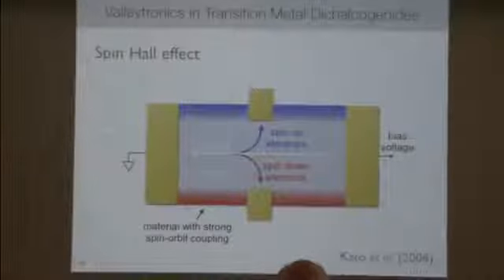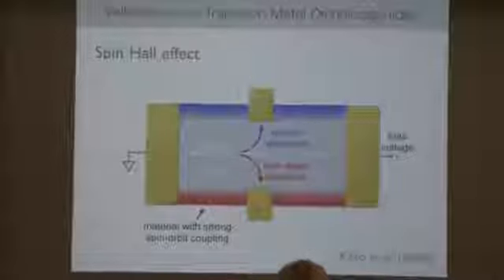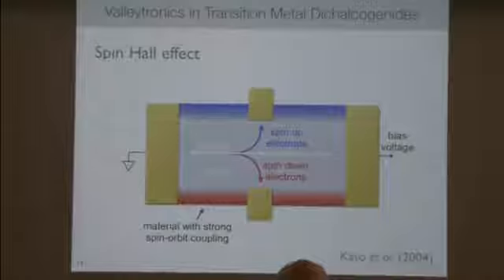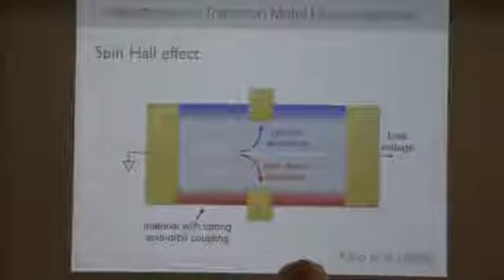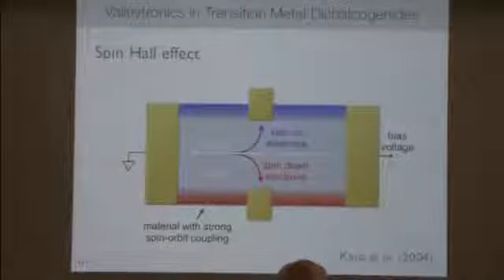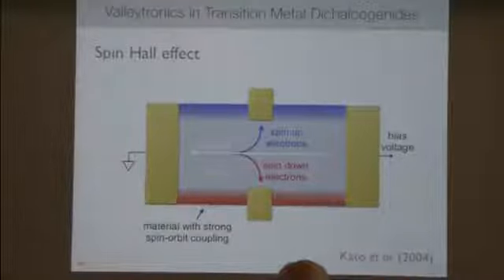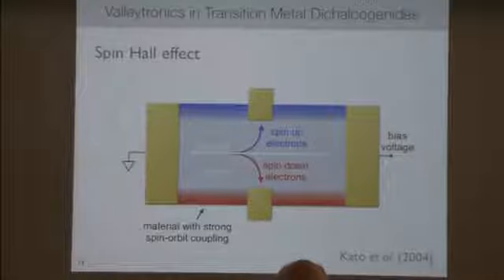About 10 years ago, it was found that there's an analog to the Hall effect for charges involving the spin of the electrons. In materials which have a strong spin-orbit coupling, which simply means that the direction of the spin of the electron is tied to its motion through the crystal, spin-up electrons can veer up in the sample and spin-down electrons can veer down. And so this segregation of spins on opposite sides of the sample was observed about 10 years ago.